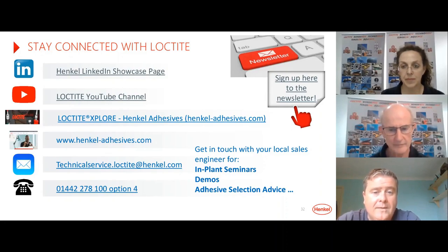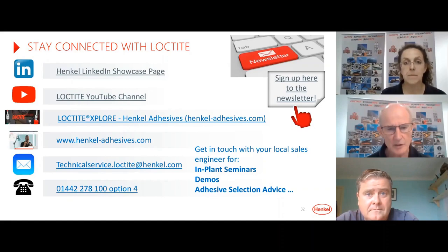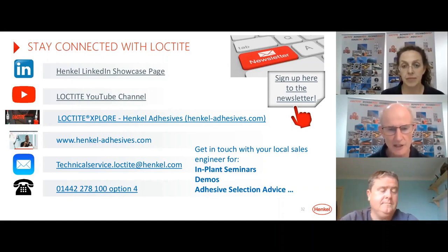And can you comment on the chemical resistance of your structural adhesives, e.g. resistance to hot, they specify 120 degree C oil? Okay, again, we would have to help the customer choose the correct adhesive for the application. Epoxies generally have very good solvent resistance, whereas something like a modified silane might struggle a bit under very hot oil.